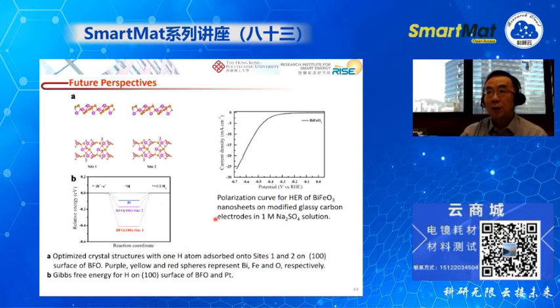field. Now, for the catalysis part, the electrocatalysis part, if we compare this bismuth ferrite to the platinum, we found although the hydrogen can be more easily absorbed on the surface of the BFO, when the hydrogen is desorbed to form hydrogen gas, it also requires a larger energy. So we measure the polarization curve for the BFO, and we found if we compare to the commercial platinum, then the property of this BFO is not as good as the commercial one.